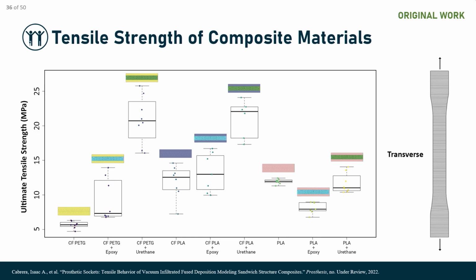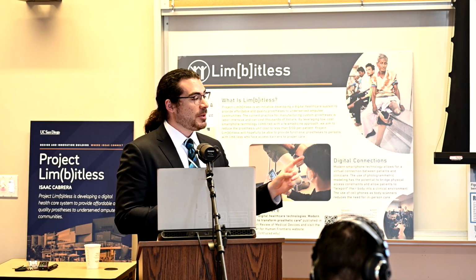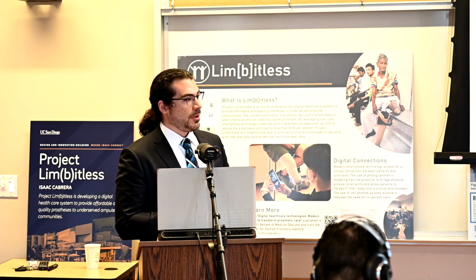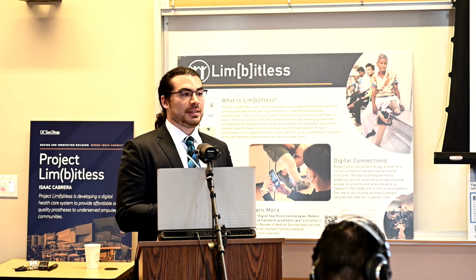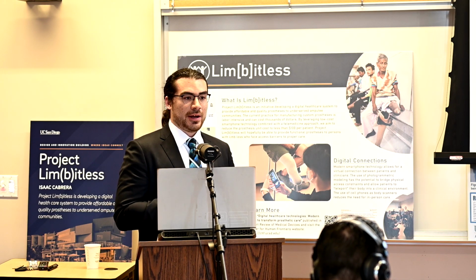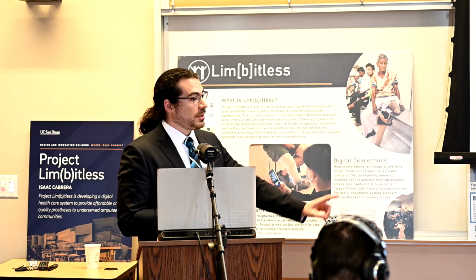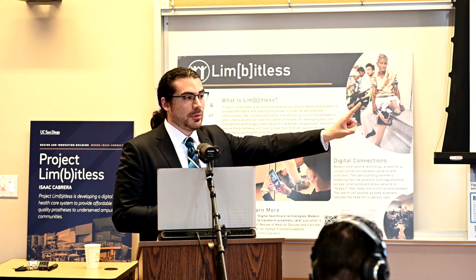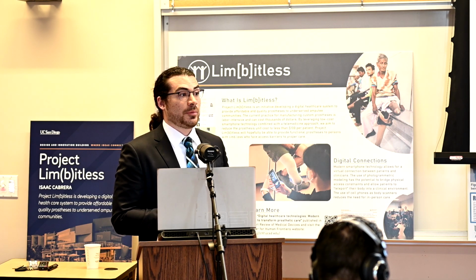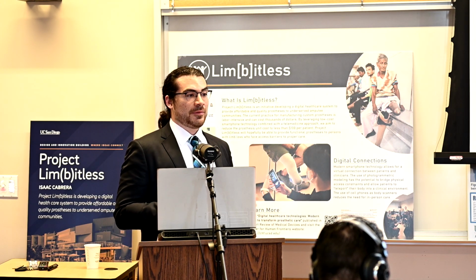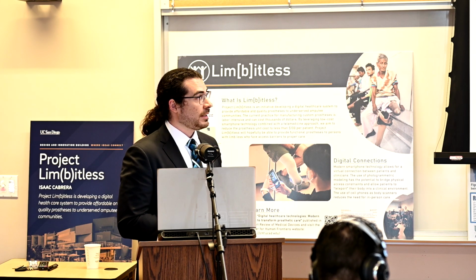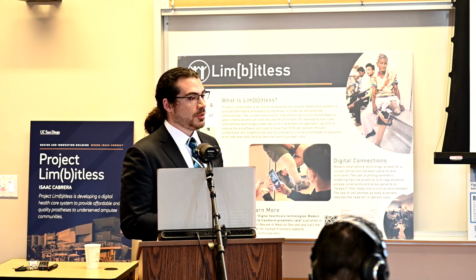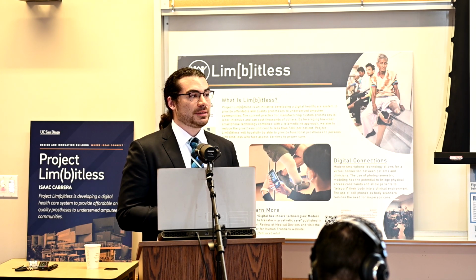So this really is good data to show that this vacuum infiltration methodology for creating these composite materials does increase the strength, especially with regards to the transverse properties, which are the weaker properties. Unfortunately, when it comes to manufacturing our prostheses, most commonly they're manufactured in the transverse orientation because of the way that 3D printers are built. So by default, you're manufacturing them in the weak orientation. With this technology and these new materials that we made, we're able to improve those properties in both the stiffness and the strength.